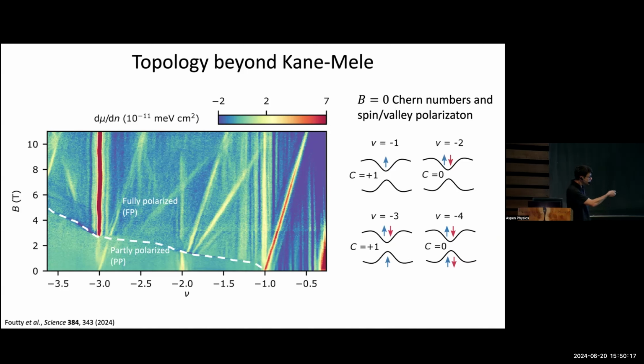And what that implies to us is that these Chern states correspond to first occupying a particular valley. They spin up, valley K. And at nu equals 2, we've occupied both valleys, and they have opposite Chern numbers. So that gives rise to a state with Chern number 0. Nu equals 3, we start to populate again one of the valleys, and again we get a Chern state, and at nu equals 4, again we've canceled out that Chern number by populating the opposite spin valley type.